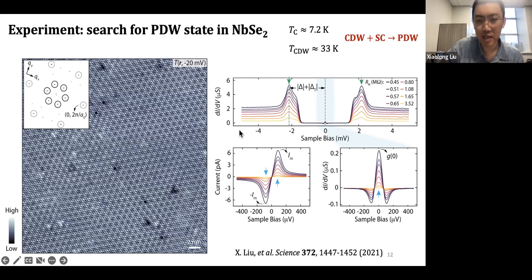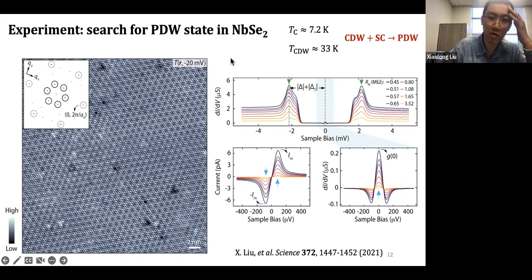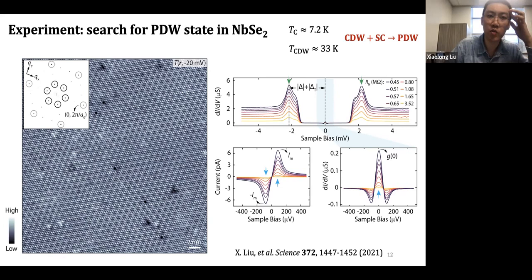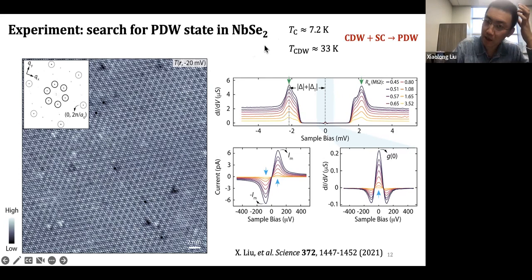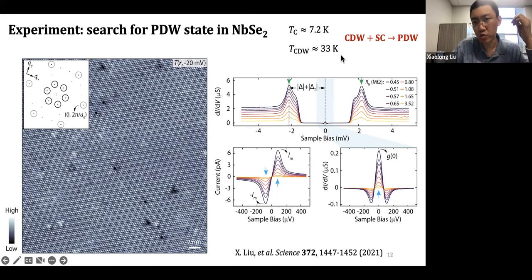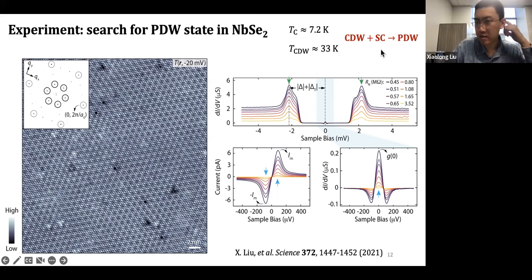I want to give background on our data before we go into UTe₂. This is our first study trying to measure pair density waves down to the atomic scale, after the detection of pair density waves in cuprates which utilized tips that were not atomically sharp. Now we are able to create superconducting atomically sharp niobium tips. The first material we look at is NbSe₂: it is well studied, very robust in superconductivity, has a high critical temperature, and the charge density wave is well known as a fundamental order. By our Ginzburg-Landau analysis, the CDW and superconductivity should give us an induced pair density wave.